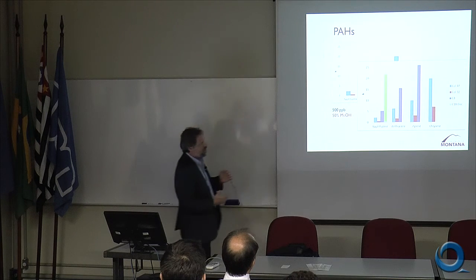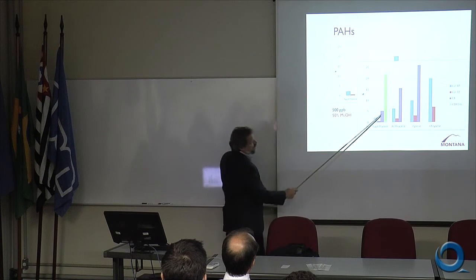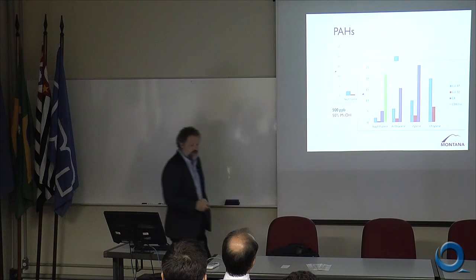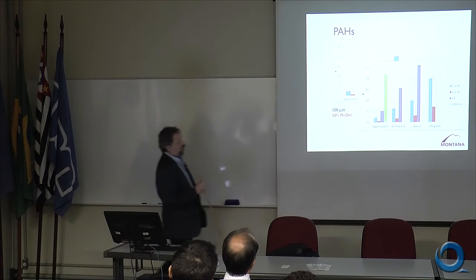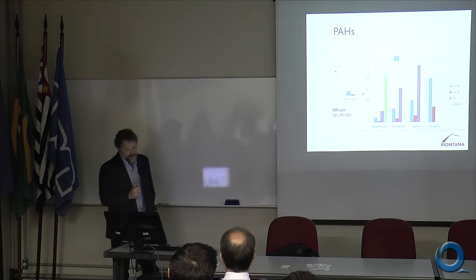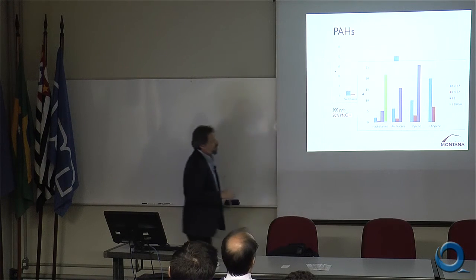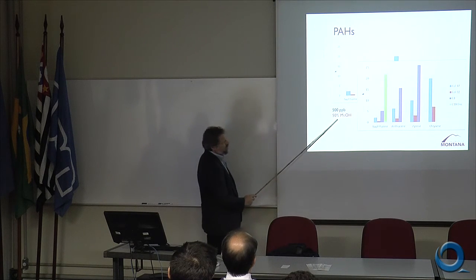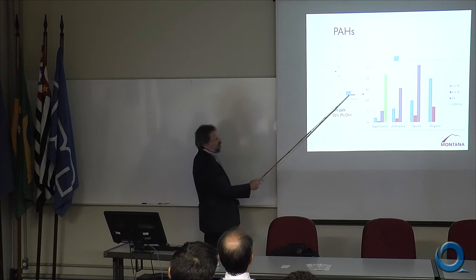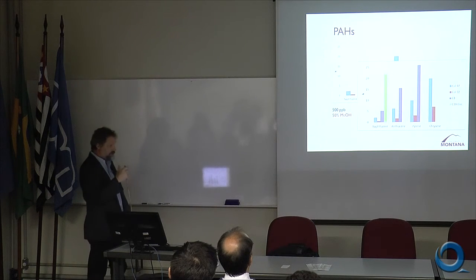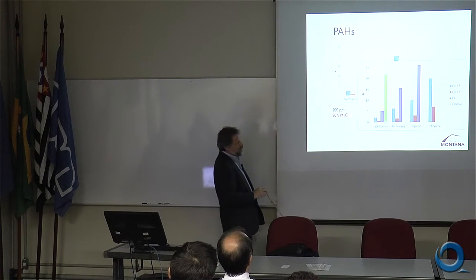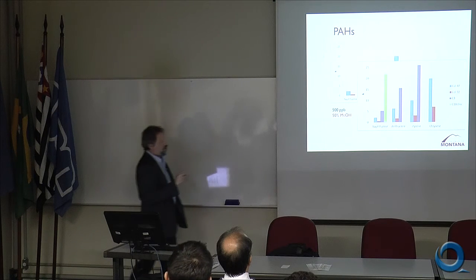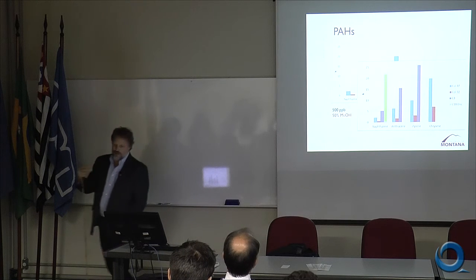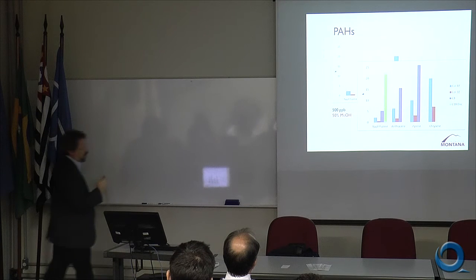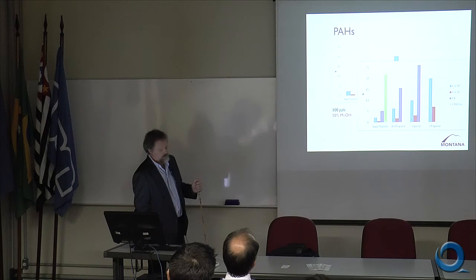Anyway, we see an increase in retention as we increase the size and hydrophobicity of the PAHs. If we compare the performance to C8 and C18, the purple bars here are C8, the green bar here is C18, and so again, conventional commercial materials are really far outperforming the nanoparticle-coated surfaces for the retention of these types of compounds. That's perhaps a bit of a negative result, but on the positive side, if we don't use 50% methanol, if we're looking at aqueous matrices, we get sufficient retention of naphthalene and all of these other PAHs to actually do an analysis and to do pre-concentration and extraction for these PAHs. And because the interaction is not quite as strong as it is with something like C18 or C8, it's a lot easier for us to elute, to desorb the PAHs from the nanoparticle-modified column. So there may be some advantage in terms of ease of recovery of these compounds after they've been adsorbed to the surface.